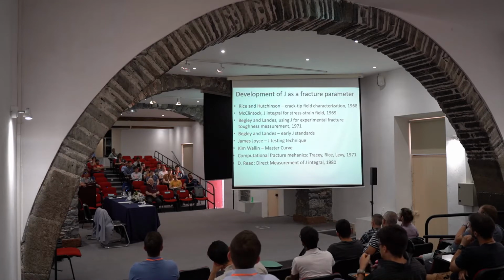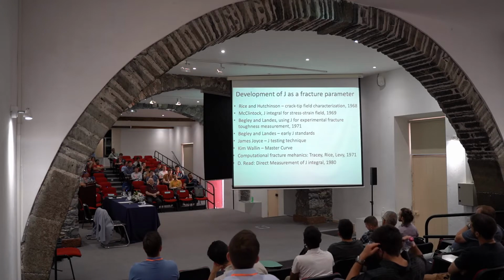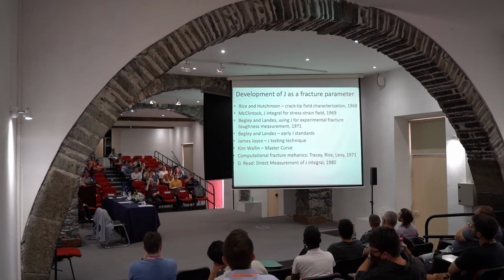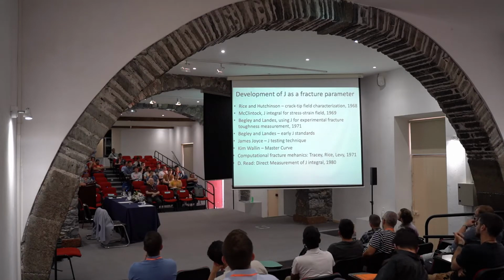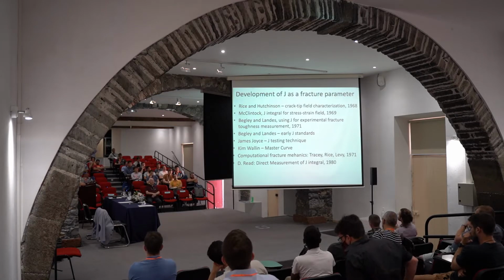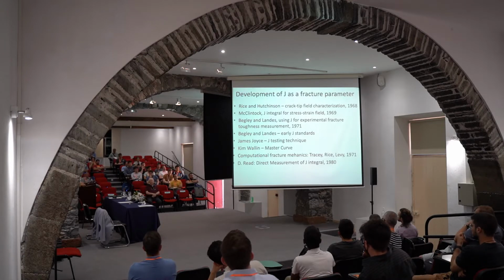So, already mentioned crack tip field characterization. That was in the same year when J integral was introduced. Then, just 2 years later, Begley and Landes first measured J integral, and that was the first experimental fracture toughness measurement with an elastic plastic parameter.